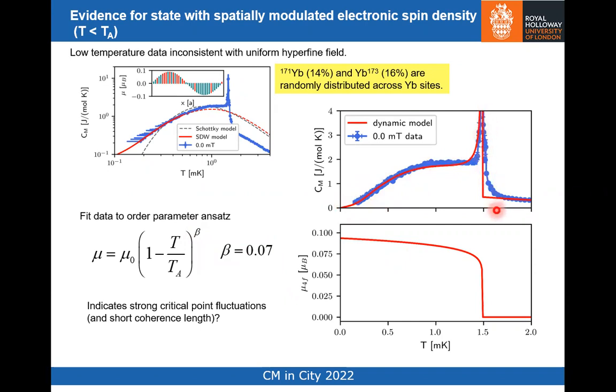That's the red line. We're again in zero magnetic field with a rather small value of the exponent, something that's in the ballpark of the exponent that you might have in an Ising type model. This exponent is not a mean field exponent. That would be, as I understand it, 0.5. So that indicates that there are strong critical point fluctuations at this temperature of 1.5 millikelvin. And that would imply a short coherence length then through the Ginzburg criterion.